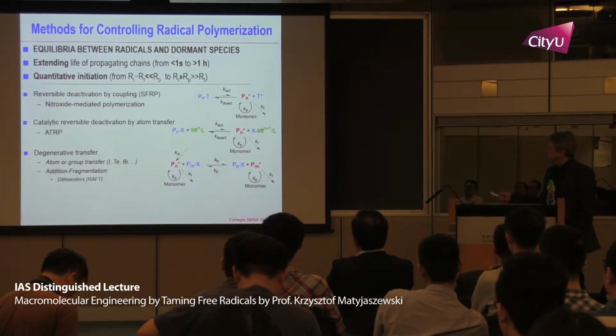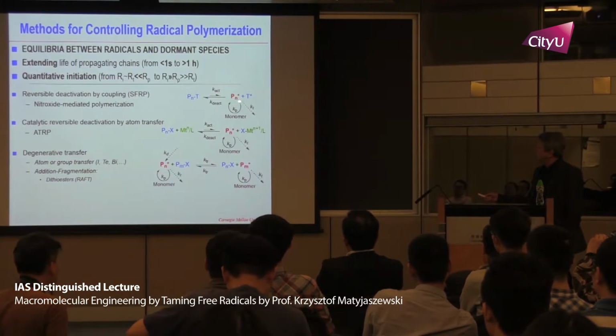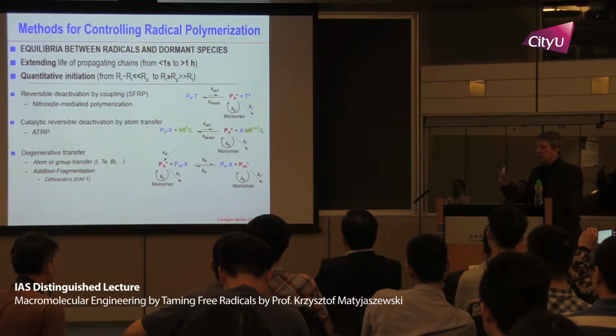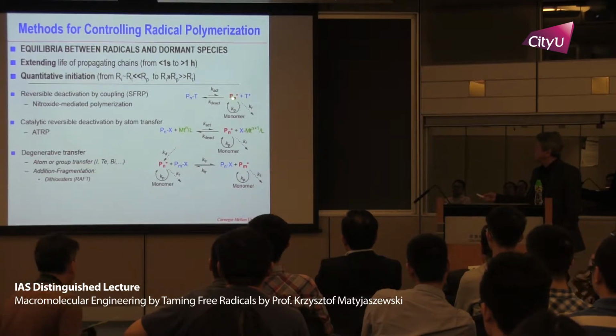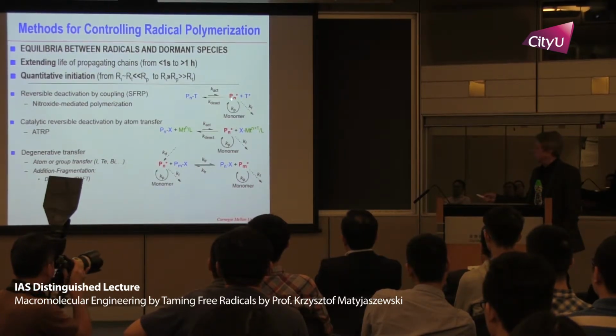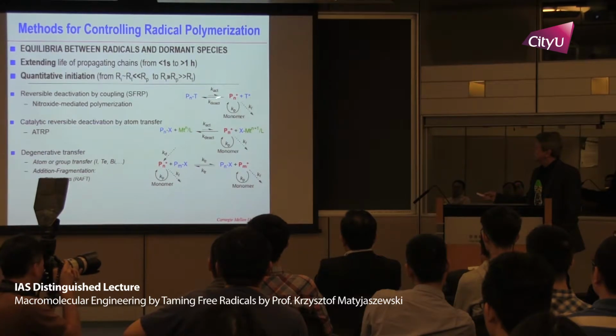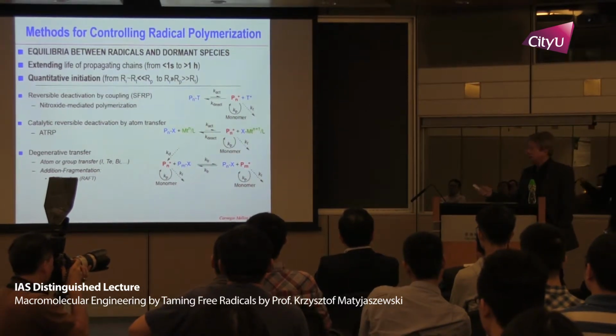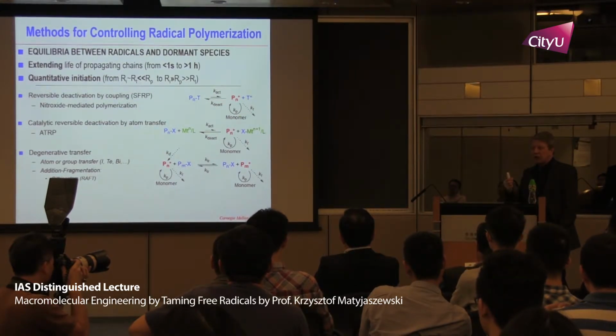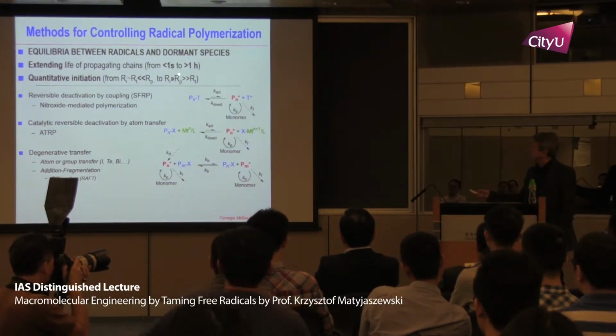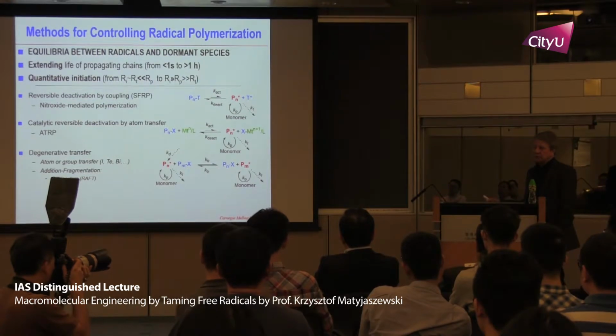So let me come back and compare conventional and controlled radical polymerization. So, as I mentioned to you, they both work with the free radicals. But normally, in a conventional radical process, monomer reacts with the chain end with the frequency 1 millisecond. So after 1 second, after 1,000 milliseconds, there is a termination process. So always was a challenge, how you can extend this 1 second time to hours and days.